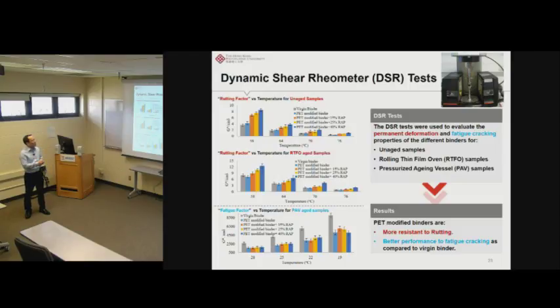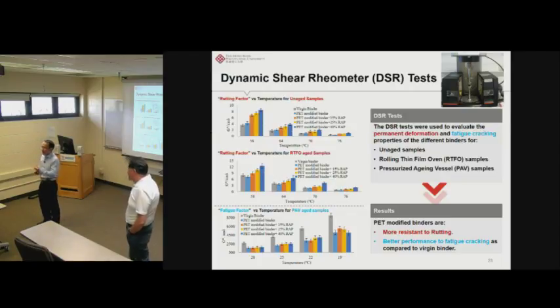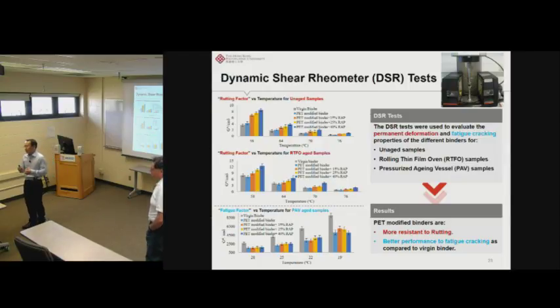Yeah, here we did test different temperatures. The original virgin binder grade is 64. It's non-modified. So we did test different temperatures, but we didn't touch the threshold value, which temperature grade it is. Actually, in Hong Kong, we haven't adopted Superpave. We partially adopted it. Like for PG76, we don't have a dash, we don't have negative 22 or something. We just have PG76 because we are not worried about its low temperature grade. So it's partially adopted in Hong Kong. Here we just want to use the Superpave binder test to show how it can change different performance properties. Other questions?